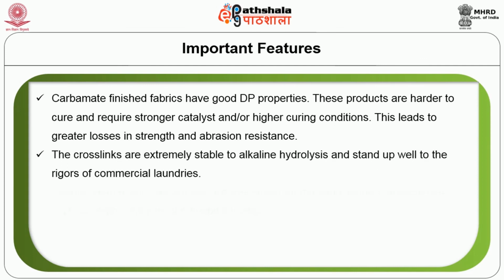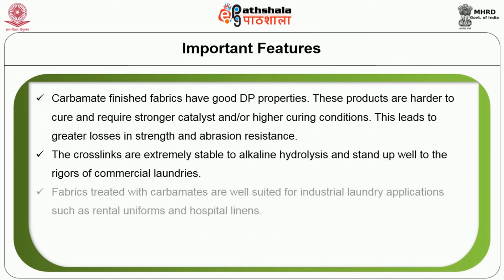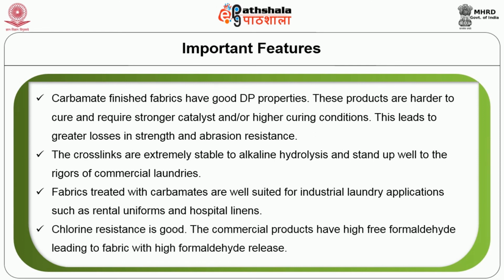The crosslinks are extremely stable to alkaline hydrolysis and stand up well to the rigors of commercial laundries. Fabrics treated with carbamates are well suited for industrial laundering applications such as rental uniforms and hospital linen. Chlorine resistance is good. The commercial products have high free formaldehyde, leading to fabric with high formaldehyde release finishes.